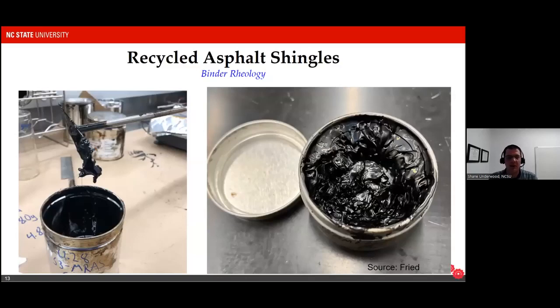So here I'm showing you a photograph from one of our students at NC State who was working with a manufactured waste shingle. So this is actually the softer of the shingles. And this binder, although it does look like it, is actually heated up to about 150 degrees Celsius. And you can see just how stiff and immovable this material is. That's even more evident on the right. Again, keep in mind, this is binder that is heated to 150 degrees Celsius or more and still behaves as a brittle solid material. So we've got big challenges when it comes to using reclaimed asphalt shingles or recycled asphalt shingles because their rheology is so very stiff.